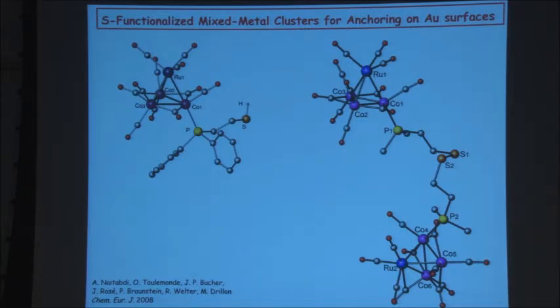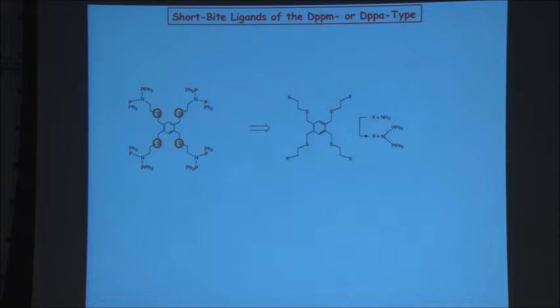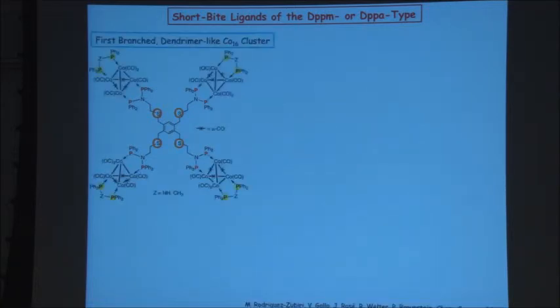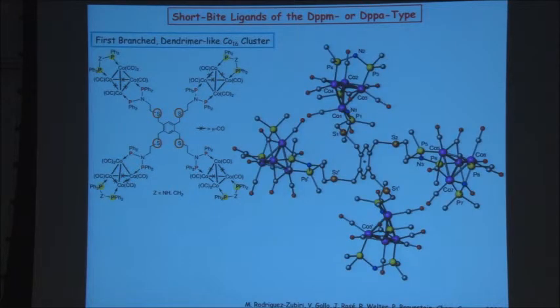So that gave us the idea to try to explore this possibility, starting from this organic ligand, which is well known, a tetrathioether, which we decorated with 1, 2, 3, 4 diphosphine moieties, which we now want to use to attach cobalt clusters, and now you can form this sort of dendrimer-like cobalt-16 cluster. How do we know that?